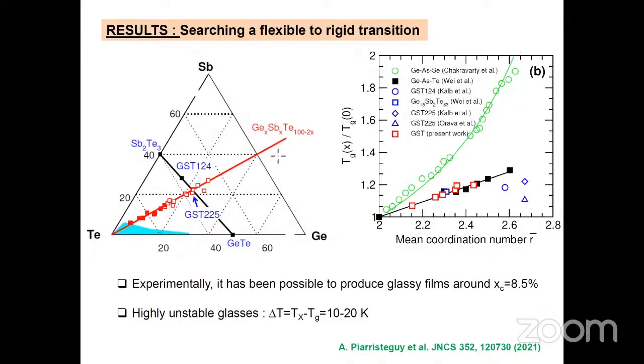And furthermore, if we analyze the glass transition temperature with respect, for example, to the mean coordination number, which is a nice way to put different systems on the same plot, we realize, that's the red symbols, that those measured glass transition temperatures have a very different behavior with respect to archetypal selenides, where basically the increase of Tg is deeply linked with the increase in connectivity. And so here the Tg seems to be much closer to an isochemical, which is GeTe. But globally, there is a very small variation of the glass transition temperature with coordination number change. And I should also mention that those glasses are highly unstable because the thermal stability, which is basically the difference between the recrystallization temperature and the glass transition temperature, is very small, about 10 to 20 degrees Kelvin.